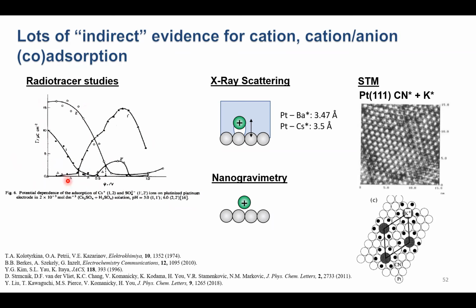It doesn't tell us where these cations are. So we could look to X-ray scattering experiments, which can actually measure the distance between a cation and, for example, a platinum electrode surface in situ. And we can see that for at least the cations that have been observed so far, they sit too close to the surface for water to sit in between the ion and the surface. And that's exactly what we're claiming we see with our DFT.